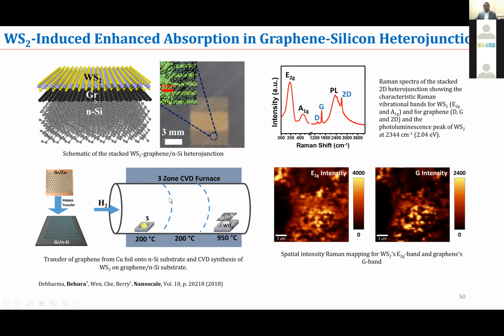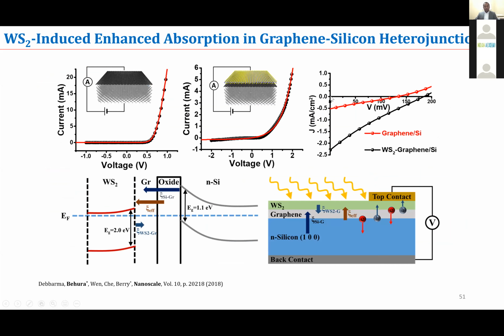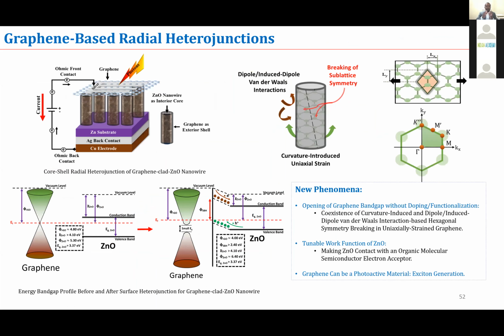And here we are able to measure higher current because of the tungsten disulfide on top, because it has high absorption. It has a high absorption coefficient compared to silicon as well as graphene. And then another type of structure which is different than the planar structures that I discussed.